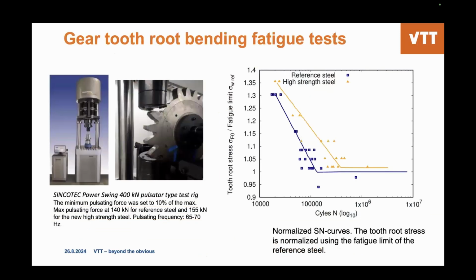And here is the pulsator type test rig we used for elaborating the S-N curve. Here are some details about the experimental setup. We have a maximum pulsating force at 140 kilonewton for the reference steel and slightly higher for the new high-strength steel. The pulsating frequency is from 65 to 70 hertz. We have many data points here. And according to this S-N curve, we noticed that the new high-strength steel actually shows better tooth root bending fatigue property.